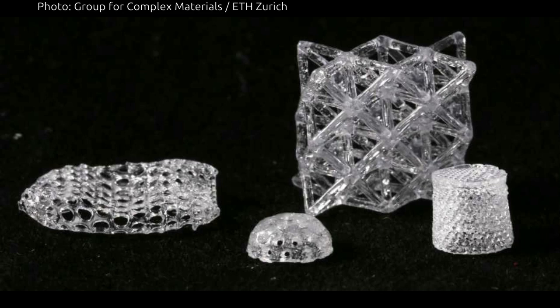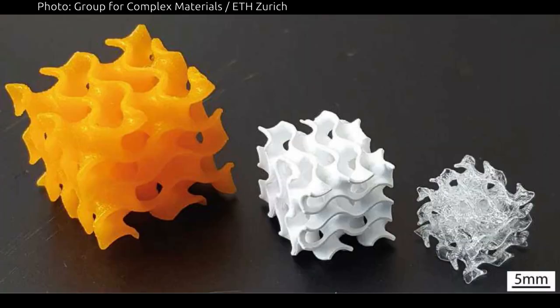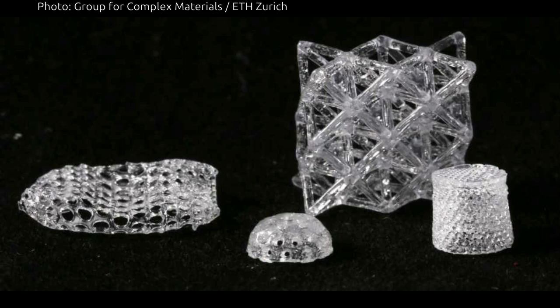The researchers then fired the blank produced in this way at two different temperatures, at 600 degrees Celsius to burn off the polymer framework and then at around 1000 degrees Celsius to densify the ceramic structure into glass. During the firing process, the objects shrink significantly but become transparent and hard like window glass. These 3D printed glass objects are still no bigger than a die. Large glass objects such as bottles, drinking glasses or window panes cannot be produced in this way.